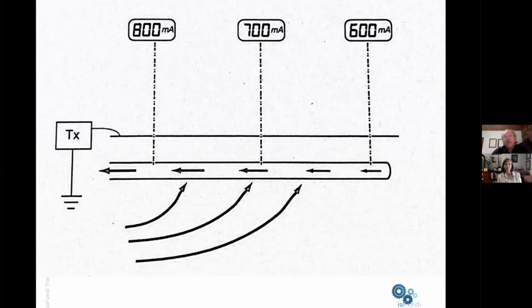Whereas the higher frequency AC systems suffer from the challenge of attenuation along the pipeline, and the signal is dissipated as a result of the pipeline's impedance and capacitance and so on, this PCM signal tends to operate more like DC. So in this photograph, with this illustration, what you're seeing is the magnitude of the current in the pipe that has been registered by the detection equipment.